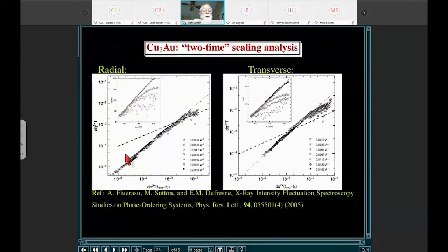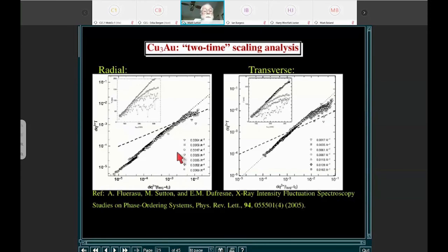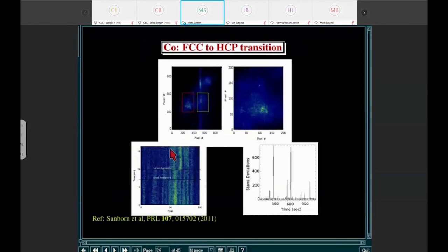From each slice, we can get a time constant, which we can look at in a super universal plot. And so here, we can look at how the dynamical scaling affects the fluctuations in the systems rather than just simply the domain size. So this is a test beyond dynamical scaling that was allowed by these measurements. There's much more information in the speckle pattern than we've taken advantage of.